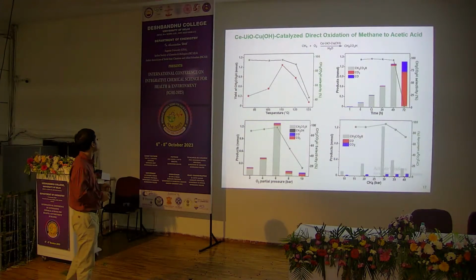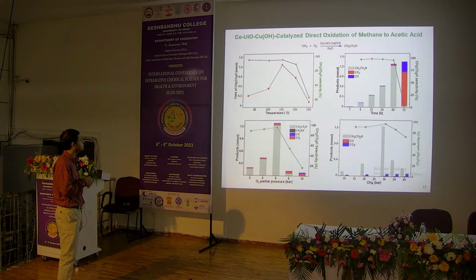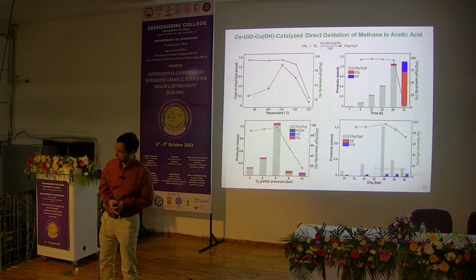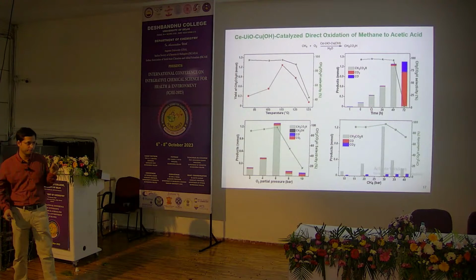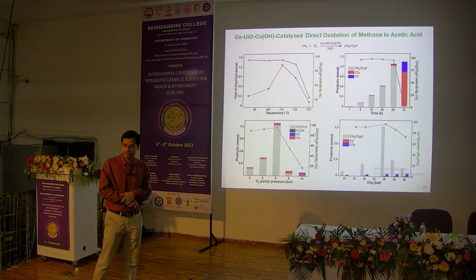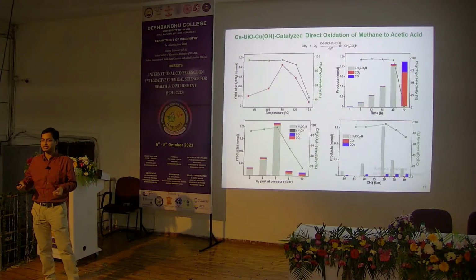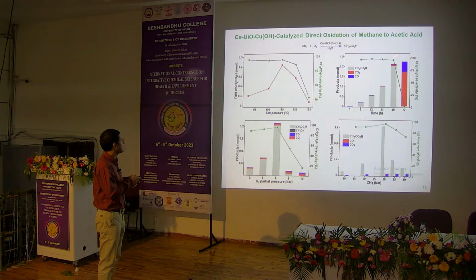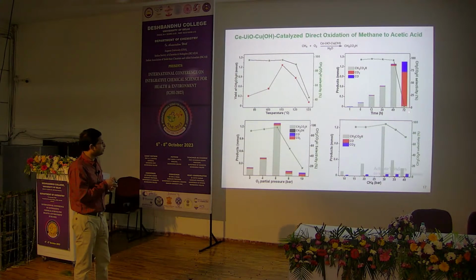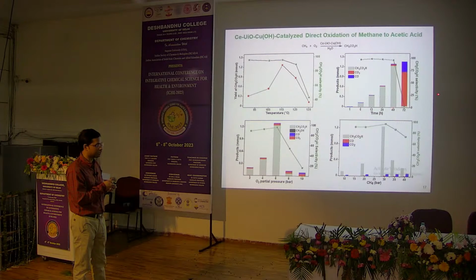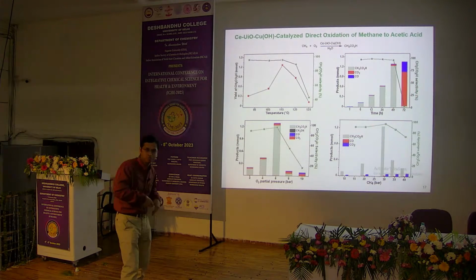We can see that the yield of acetic acid increases with temperature, and the maximum yield is obtained at 115 degrees centigrade. Beyond 115 degrees centigrade, the yield of acetic acid decreases significantly. That is because the MOF degrades at high temperature. That is one of the defects of this material. Also at high temperature, the acetic acid product degrades to methane and carbon dioxide. We also varied the time. At 40 hours we got the optimum yield. Beyond 40 hours we have to stop the methane oxidation reaction, because the acetic acid is further converted to carbon dioxide.